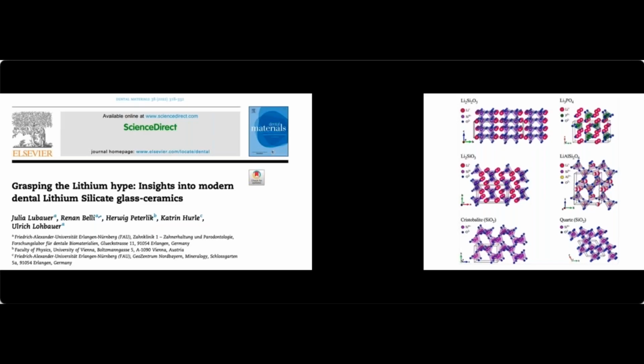Are all lithium materials, are all these different brands of lithium silicate the same? No, when you look under the microscope, each of them is crystal-wise a little bit different. But as a group, the lithium silicates are so close to each other in characteristics when you compare them with a resin or a hybrid or a glass ceramic that we can bunch them all together, just like we do with the glass ceramic, and say, hey, this is how they behave. How do they behave? They're much more resilient than glass ceramics, because the way the crystals grow on a lithium silicate is different than the way the amorphous crystal of a glass ceramic is.